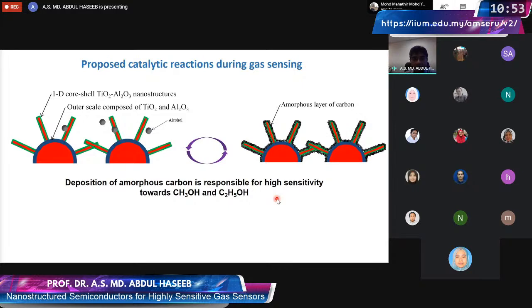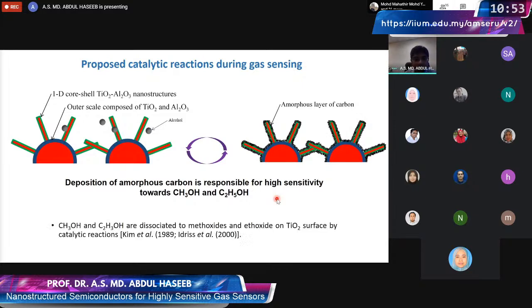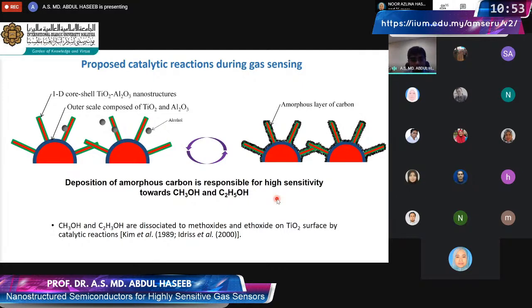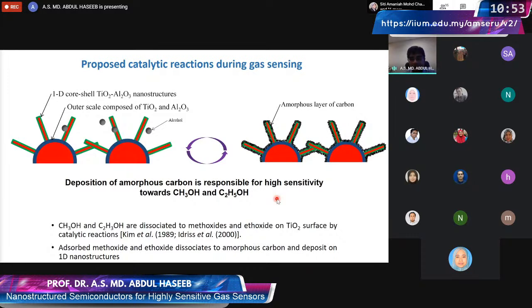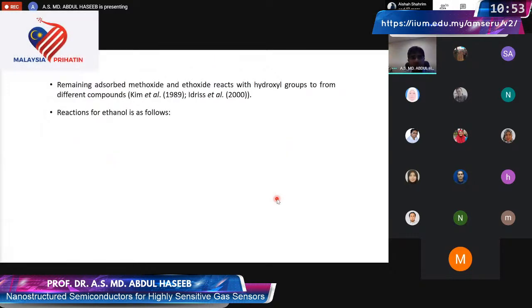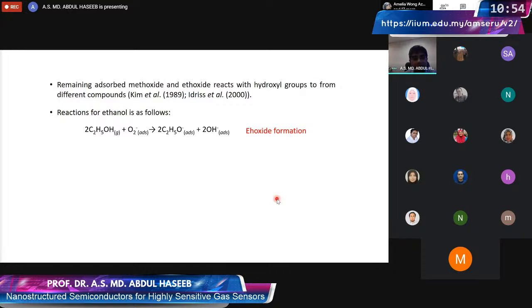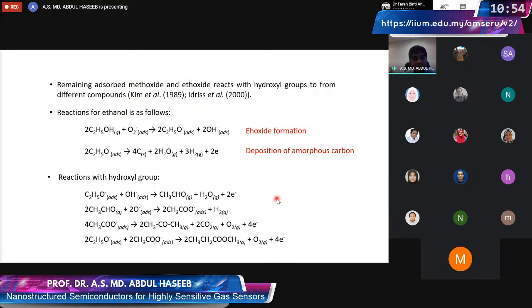And what we find in that literature is that when we expose our oxides at high temperature to those gases, they are dissociated into methoxides and ethoxides. And it's interesting that as a result of those interactions, a series of reactions can happen. So the ethoxide formation can happen. Ultimately, after that, there is deposition of this amorphous carbon from these ethoxides, that we have seen, and then some other reactions involving hydroxyls also happen if they are present there.